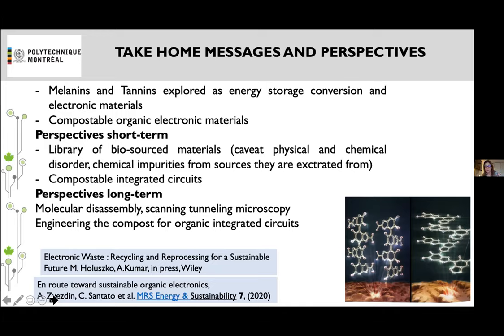So these materials work, definitely they work, and the devices fabricated based thereon have decent performance and decent stability. So this legend that pseudocapacitors, or anyway when you have a redox species on carbon, you have delamination after a few cycles, is not always true. In aqueous media, as I was saying, we ran 20,000 cycles, so it's acceptable.